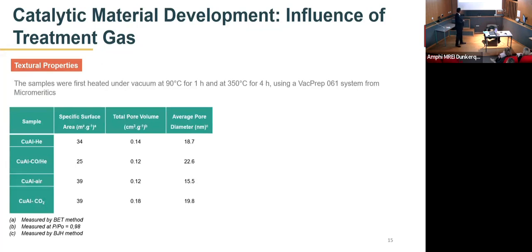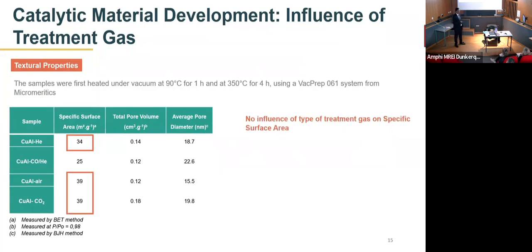In order to see the effect of the treatment gas on the different material properties, first we did some characterizations. The first characterization was N2 physisorption, because we wanted to see the difference in the textural properties. We compared the specific surface area, the total pore volume, and the pore diameter for the different samples. The first thing that we noticed was that not a great influence of the treatment gas was found on the specific surface area of the mixed oxide samples. However, the lowest specific surface area was recorded for the carbon monoxide treated sample, which was supposed to be because of the highly reducing gas, carbon monoxide diluted in helium, which has resulted in sintering of the particles, and so we have a decrease in the specific surface area.